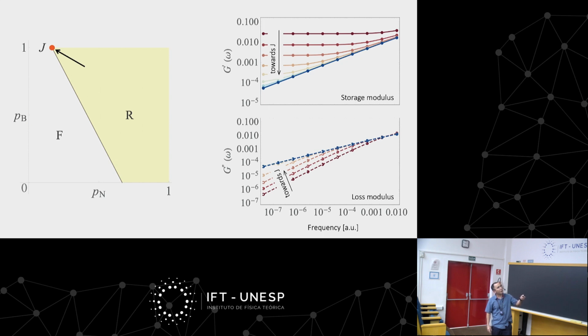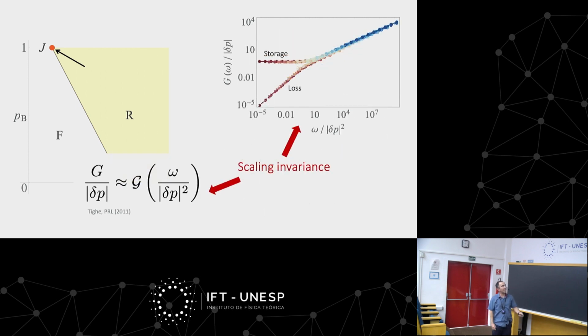And the first thing that you'll realize when you stare at a plot like this is that they are in log-log scale, and they all look like the same curve, except they are shifted in this log-log scale. And this is a hint that there is some sort of scaling invariance at play there. The idea is that you can rescale G prime and the frequency here to collapse this data. If there is this scaling invariance, you can collapse this data by doing this appropriate rescaling. And as it happens, you can do something like that and you get very nice collapse.